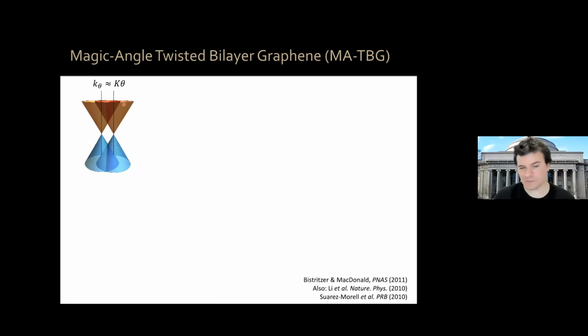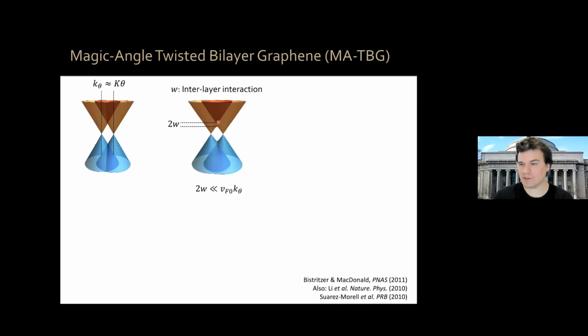between the 2 sheets. This leads to bonding, anti-bonding states, okay, due to this interlayer tunneling or interaction, so that the gap opens with one band being pushed down in energy and the other band being pushed up in energy. Okay? You can think of this as the same thing as bonding and antibonding states in a hydrogen molecule, except that now it's a giant graphene molecule, 2 graphene sheets coupled. Okay.